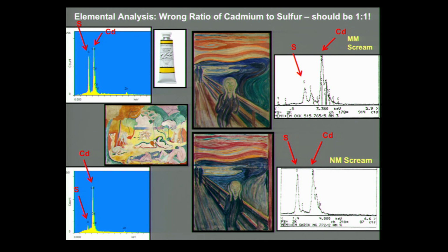So when we do elemental analysis of this paint, it turns out that we have the wrong ratio of cadmium to sulfur in the paints that are fading or darkening. And so I did this experiment just by going to the art supply store and buying a tube of cadmium yellow paint. And we should expect a 1-to-1 ratio of cadmium to sulfur, and that's essentially what we see in the brand new tube of cadmium yellow. And it's also what we see in the National Museum Scream that's in such good condition. But if we look at the Munch Museum Scream, you can see that there's very little sulfur left. And if we look at the Joy of Life, there's almost no sulfur left at all.